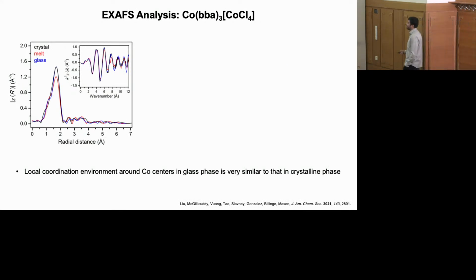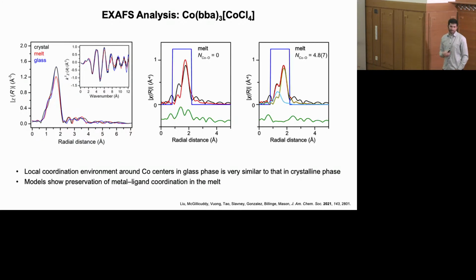We can also look at exactly how the structures of these extended frameworks change as we go from the crystalline solid state to the liquid state and then back to the glass state. So we can do EXAFS experiments, extended X-ray absorption fine structure experiments, where we shoot an X-ray beam at these materials. And this will eject an electron specifically from the metal atoms within the material. And then we effectively look at interference of this electron as it leaves the metal center. And this tells us about the local coordination environment around the metal. And so what we find is that in a lot of these materials, the local coordination environment around the metal center is not all that different between the crystalline solid and the liquid state. And this is exactly what we were hoping for, because we want to be able to use these very directional bonds between our metals and bridging organic ligands to influence the average local structure within the liquid and then the glass that it's quenched from it.